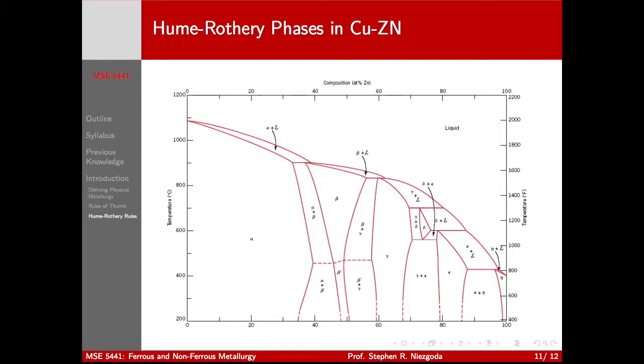So these stable phases where you would ordinarily not expect to make a solid solution are called Hume-Rothery phases, where you get these lines separated by miscibility gaps. And this is completely due to the electronic structure at that point stabilizing. So your FCC at this end, HCP at this end, and then honestly, I don't remember off the top of my head. We'll talk more about this when we hit brasses.